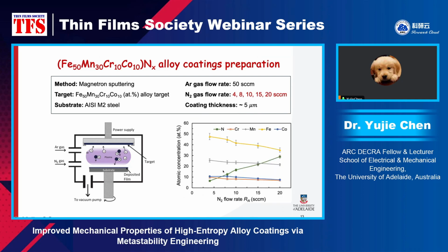So here I'm showing you the composition of these 5 coatings. As we can see, the nitrogen content, this blue line here, increases from about 7 atomic percent to about 30 atomic percent when the nitrogen gas flow rate increases from 4 to 20 SCCM. And at the same time, as the nitrogen content increases, all the metal content decreases. But the ratio between these 4 metal elements agrees very well with the target composition.